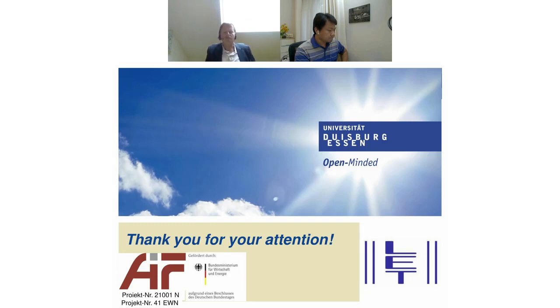Yes. The standard nickel zinc battery is well known and has good performance, and we want to try our slurry approach also on the nickel side of the battery. But of course, there's one problem: the nickel oxide is not conductive, it's not zinc. So we need a conductive coating on the particles, and this is one part of the experimental program.